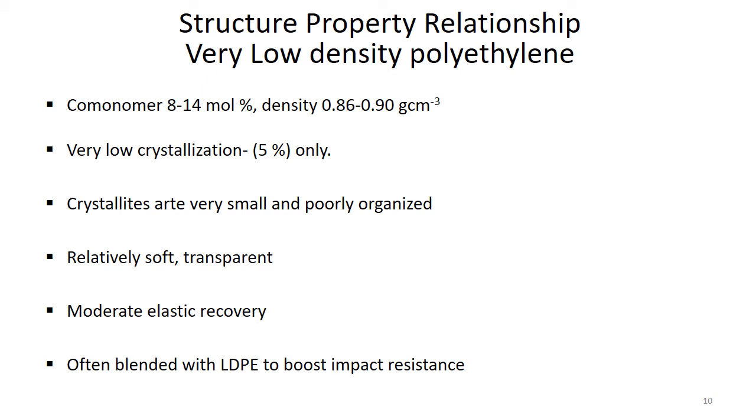We polymerize these resins using a single site catalyst, which gives us relatively narrow molecular weight and very uniform distribution of polyethylene chains. When we talk about their properties, they are relatively soft and transparent because they are largely non-crystalline in nature. Films made from these materials are resilient with a moderate level of elastic recovery, as long as they are not stretched beyond strain levels of approximately 100%.